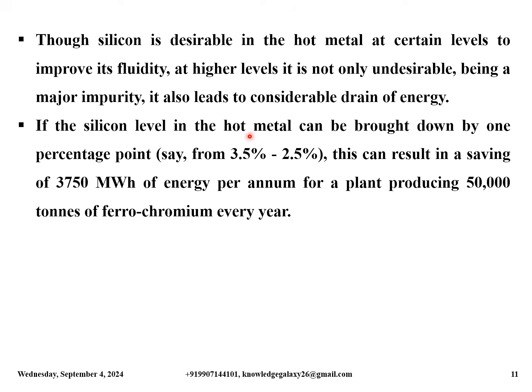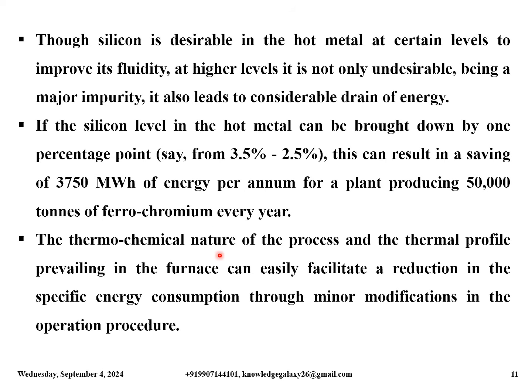If the silicon level in the hot metal can be brought down by 1 percentage point, say from 3.5% to 2.5%, this can result in a saving of 3,750 megawatt hour of energy per annum for a plant producing 50,000 tons of ferrochromium every year. The thermochemical nature of the process and the thermal profile prevailing in the furnace can easily facilitate a reduction in the specific energy consumption through minor modifications in the operational procedures.